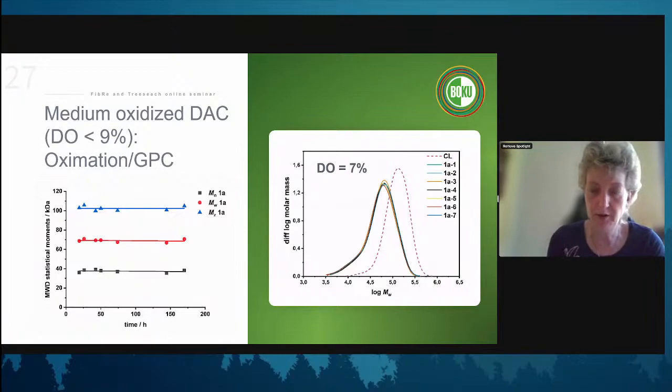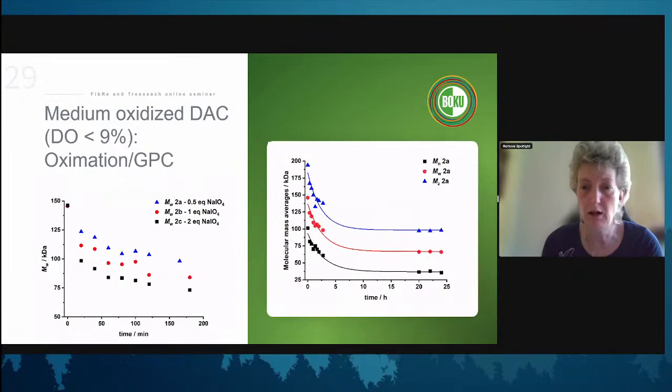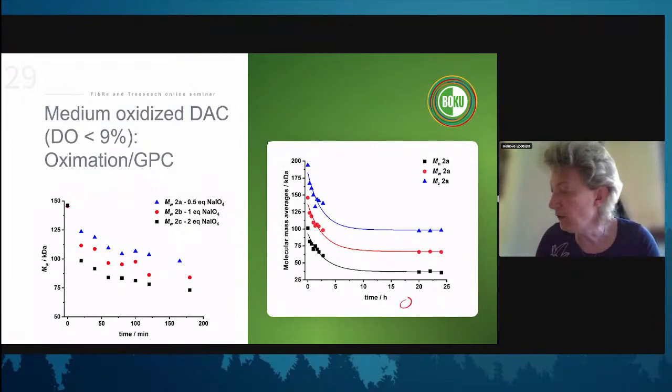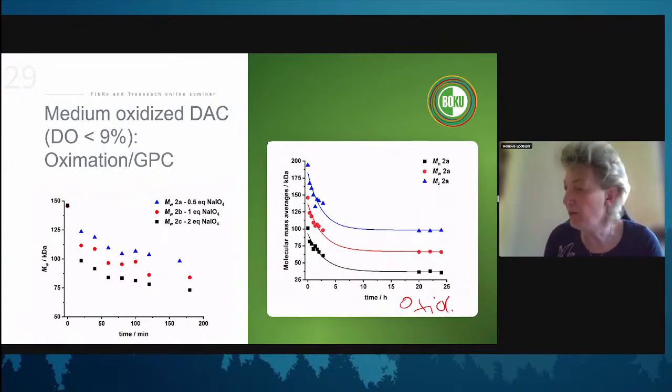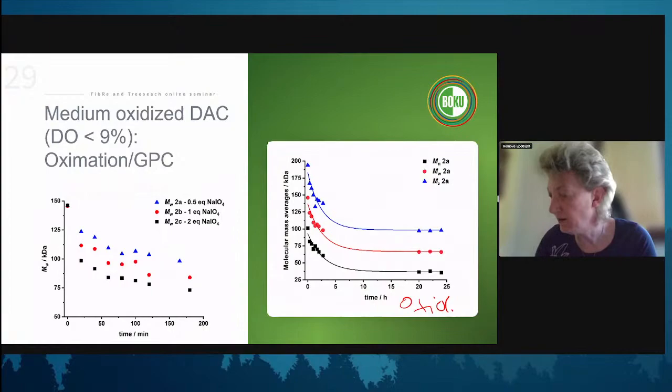And this is now not induced by the GPC. This is in a way real. Something like this can now basically be measured. And we can also now follow our oxidation. So time here is time of oxidation. And we can follow the molar mass degradation basically during its oxidation.